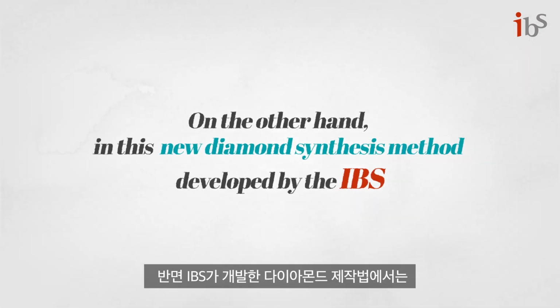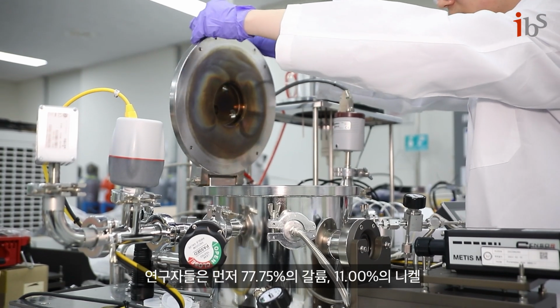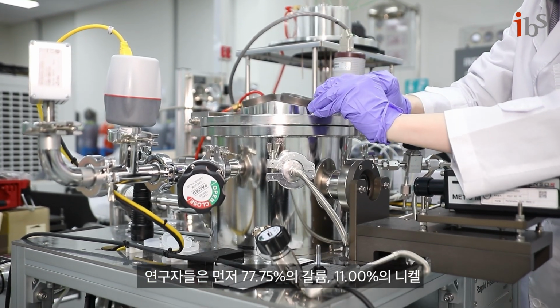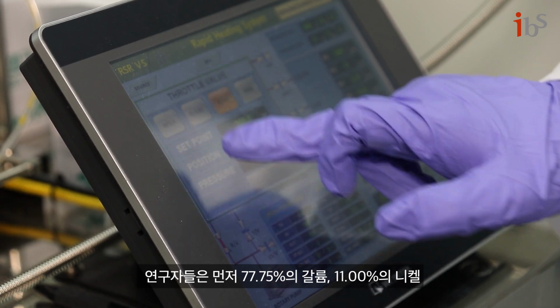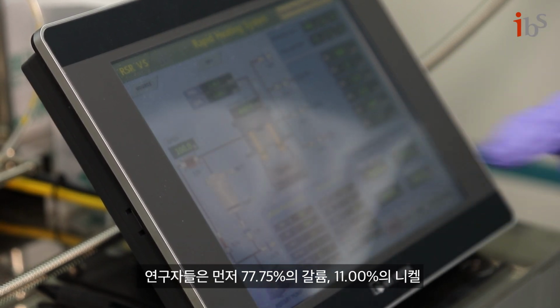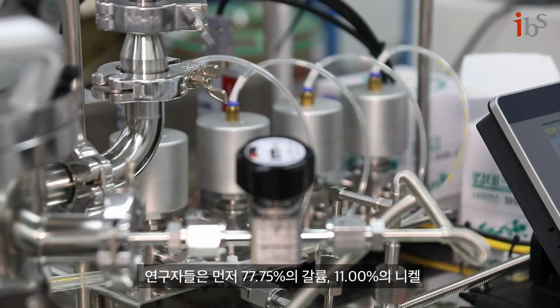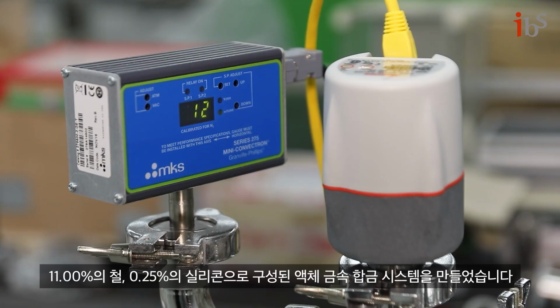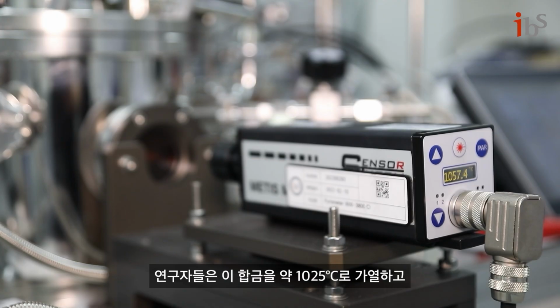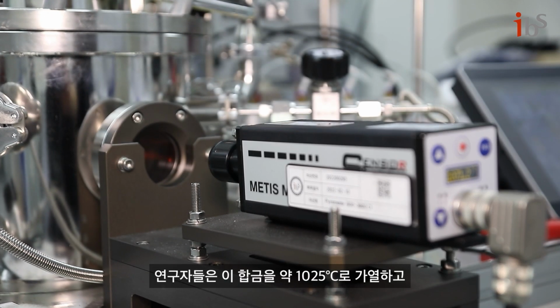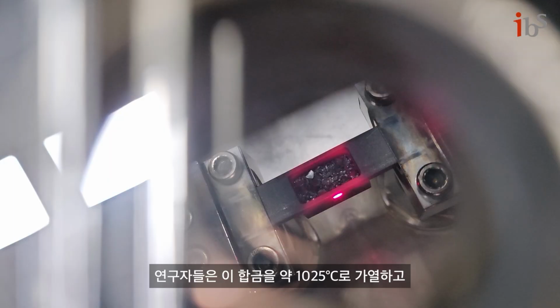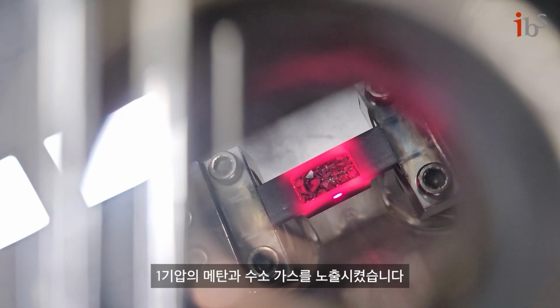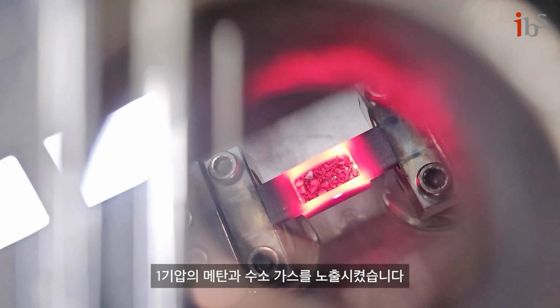On the other hand, in this new diamond synthesis method developed by the IBS, researchers first made a liquid metal alloy system consisting of 77.75% gallium, 11% nickel, 11% iron, and 0.25% silicon. The researchers then heated the alloy in a chamber to 1025 degrees C and exposed it to methane and hydrogen gases under 1 atmosphere pressure.